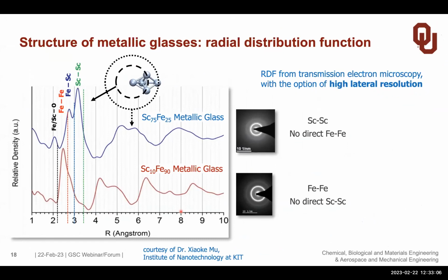You can also look at it in a different way, for example, by using the radial distribution function. And the radial distribution function you can measure by using neutrons as a particle to do the diffraction, or you can use X-ray diffraction in the synchrotron, or to have also local information, you can do it in the electron microscope. And this is an example of the radial distribution function, so kind of the probability to find another atom or other atoms in a coordination around a central atom. So this is shown here.